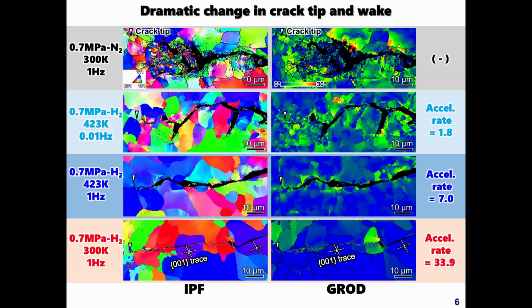And also these fatigue crack pathways at straight part with extremely low GROD value was parallel to the 001 plane analyzed by the two plane tracing methods. So this tendency is very similar to our previous studies. By comparing the different loading frequencies at highest temperature, you can find the apparent difference between them. So the loading frequency affects the crack propagation fashion in the gaseous hydrogen environment. But I confirmed that the loading frequency did not affect the fatigue crack growth rate in nitrogen gas.